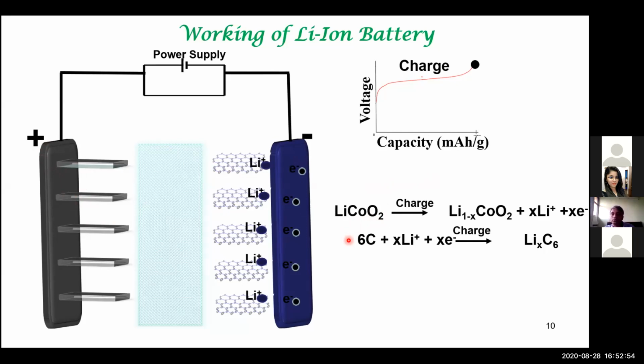So when you charge the battery, you have moved the lithium from the positive electrode, the cathode in this case, to the negative electrode. By this process, you have increased the energy of the system. When you take the lithium from the transition metal oxide, cobalt oxide, and put it, by intercalation, which is the technical term, into the graphite, in between the graphite layers, you have increased the energy of the system.